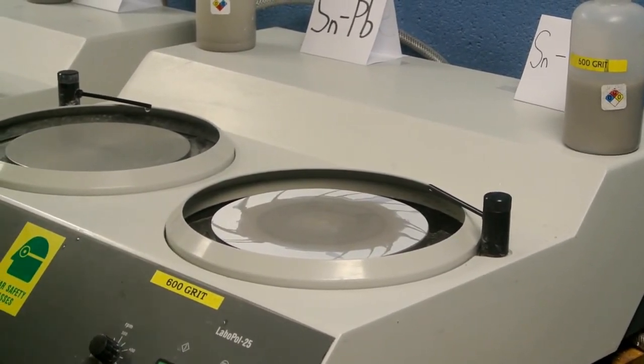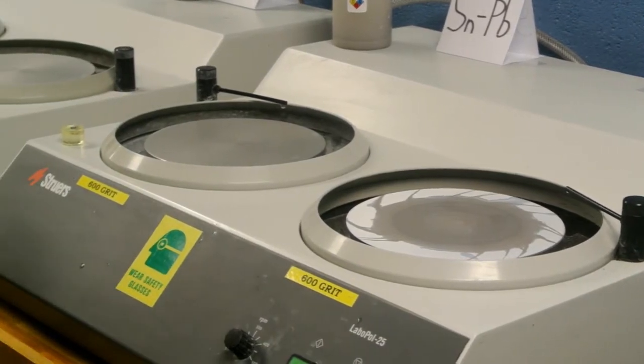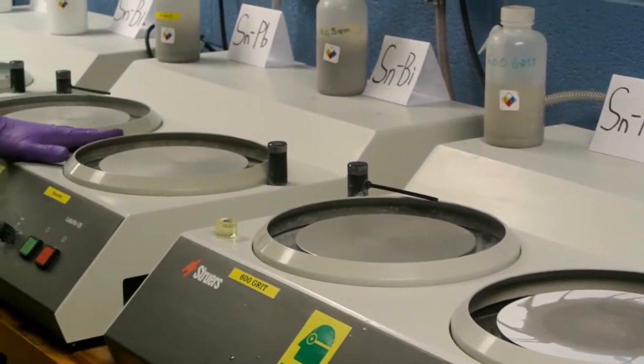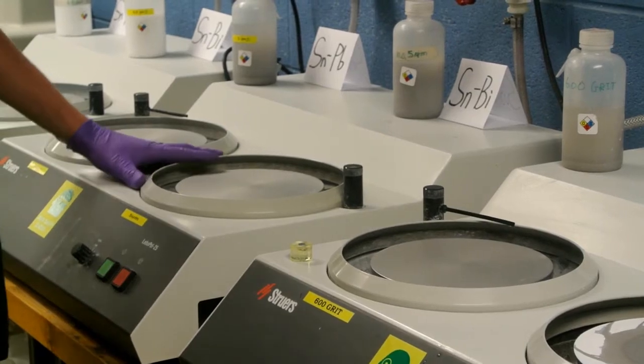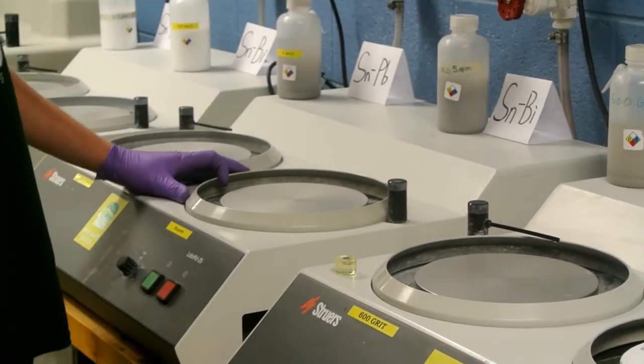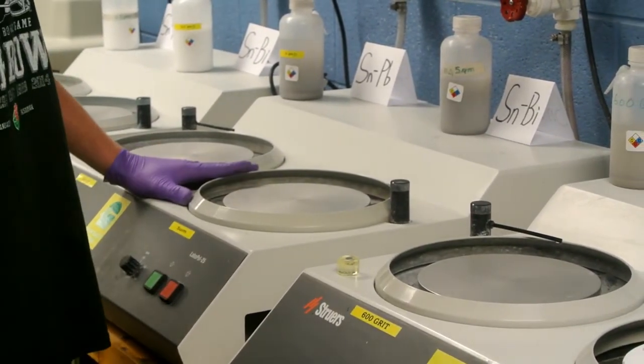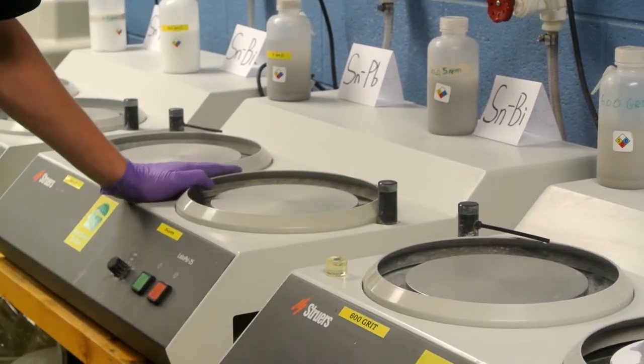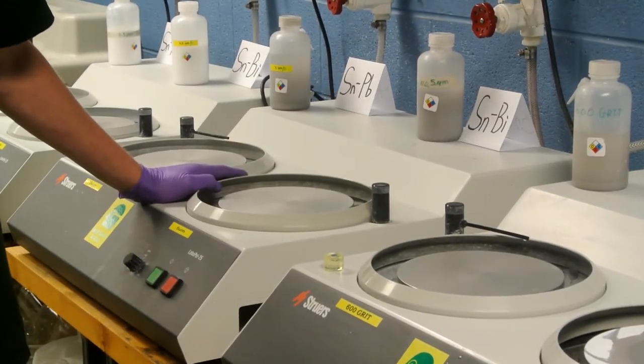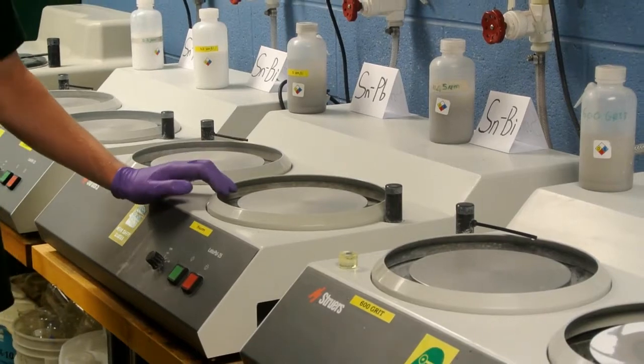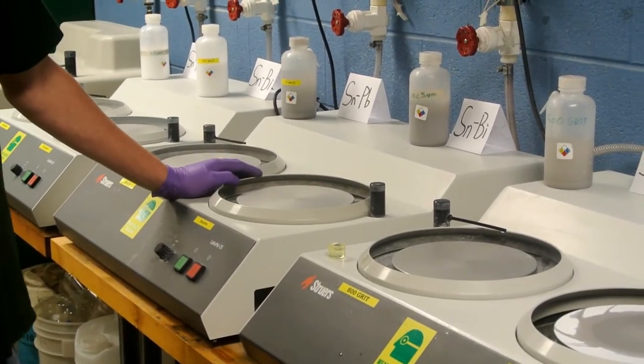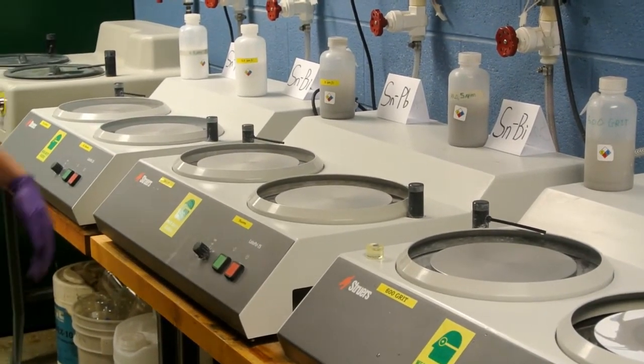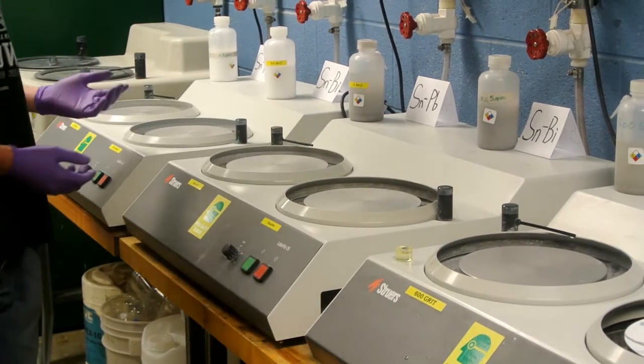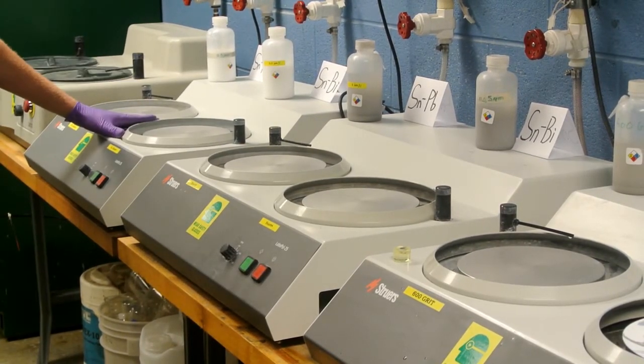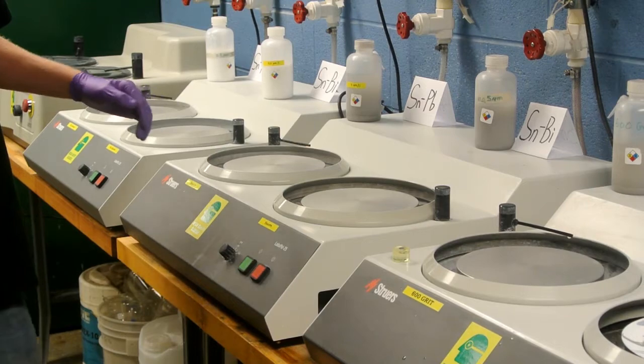While 600 grit's purpose is really to get rid of the silicon carbide, 5 micron is where you really start to see the scratches go away. So if you're thinking you're done with 5 micron and you still see scratches, you're not done. But if you see a single small scratch, you will most likely be good. You can just move on to 0.3 micron.